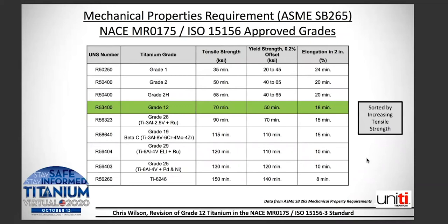Okay, so looking at the mechanical properties of those grades and sorting them by increased tensile strength. Now the mechanical properties are coming from ASME SB 265. There are really no specific mechanical properties within the NACE standard. But if you look at the ASME standard and sort them by tensile strength, you can see the green rows, the grade 12, falls sort of in the middle of the pack. Obviously not as high of a tensile strength or high properties as the alloyed grades, but a significant improvement over mechanical properties of the grade 2/grade 2H.